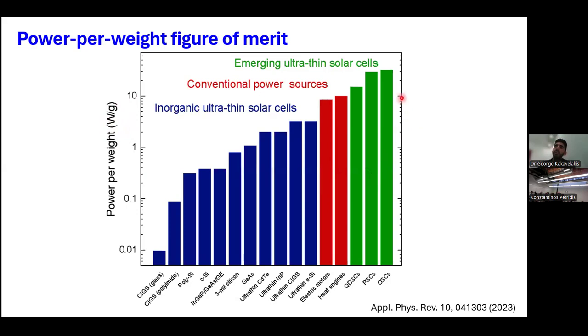Okay. And we have done some calculation, and this is a paper that we published a few years ago. According to the literature, for crystalline silicon it is 0.5 watt per gram. For extremely thin amorphous silicon it is around 5, while for perovskite and other emerging photovoltaics, it can reach even 30 watt per gram. And this is experimental, not theoretical. So you see already two orders of magnitude better than crystalline silicon. Okay, so there is a significant potential for commercialization.